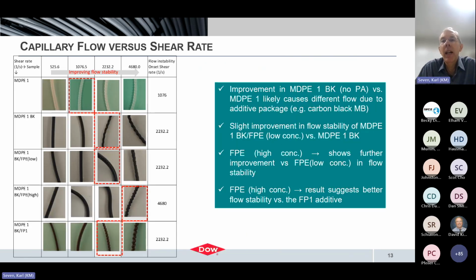So the capillary rheology test was also used to evaluate the samples for melt fracture, and I'm showing those results. This is basically capturing the lowest shear rate at which signs of flow instability show up for some of these samples. MDPE1 is our comparative polymer sample, and we start to see flow instability at 1076 1/s. Then as we go to the fully formulated jacket compound, MDPE1 BK, there's some improvement there, as can be seen in the pictures. You have to look a little closely, but you see the flow instability in the strand itself at a higher shear rate.